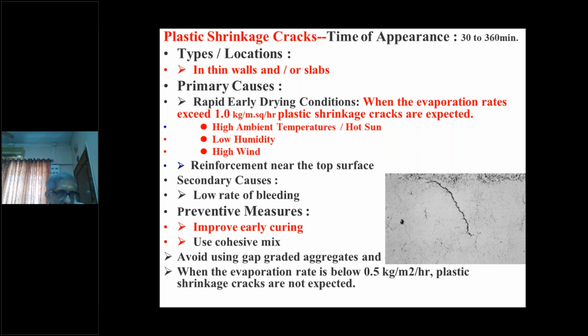Low rate of bleeding. Mind you, we say when water comes out of concrete, concrete is bleeding. Water is supposed to be the blood of concrete. Now, when the rate of bleeding is high, water collects on the surface and in one way protects the concrete from cracking because it maintains good humidity on it, and of course when it evaporates it gives cooling to the top surface. If the rate of bleeding is low then it will not give the protection and therefore concrete will start cracking. The remedy is to use cohesive mixes, avoid gap grading of aggregates and cement.